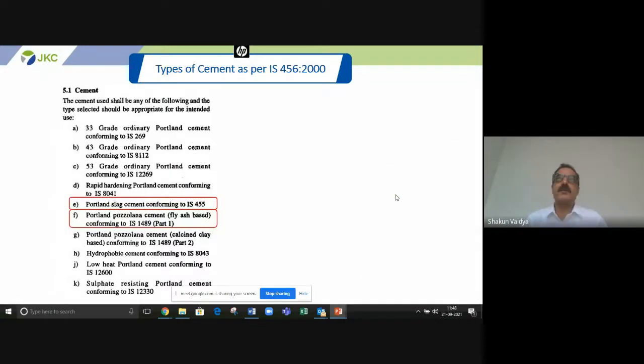So, typical types of cements as per IS 456-2000, we have OPC grades of 33, 43, 53. Now, this has also changed. The IS number is now IS 269 for 43 and 53 as well. So, it is IS 269 33, IS 269 43, and IS 269 53 now. And then we have other variants, but the most widely used material is PPC, Portland Pozzolana cement. And then in east and parts of south, we have slag cement. And the latest variant is composite cement, which has not been enlisted in IS 456-2000, the latest edition of IS 456. But we have a BIS code for that, so it is also there. And apart from that, some special types of cements are also there.